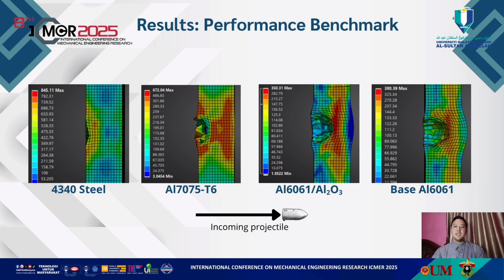Now we take a look at the image. The stress distribution in the 4340 steel plate is characteristic of a very hard and tough material. The simulation shows that the high stress zone is highly concentrated in a tight, bulb-like shape directly beneath the projectile. This indicates that the material's high strength resists the projectile in a localized area, efficiently absorbing the impact energy without significant damage propagation.